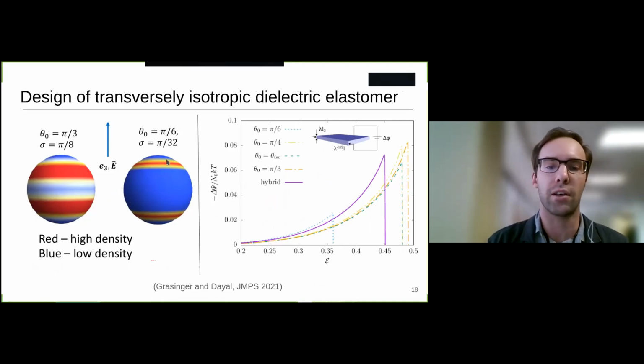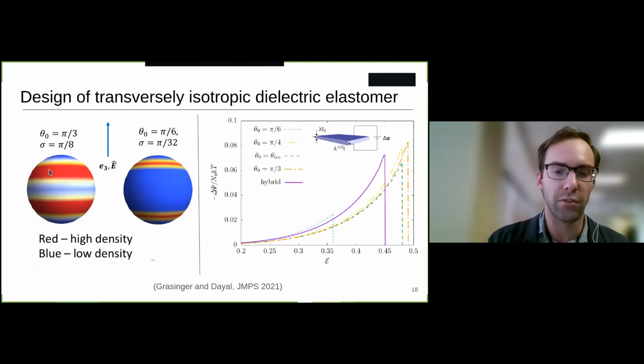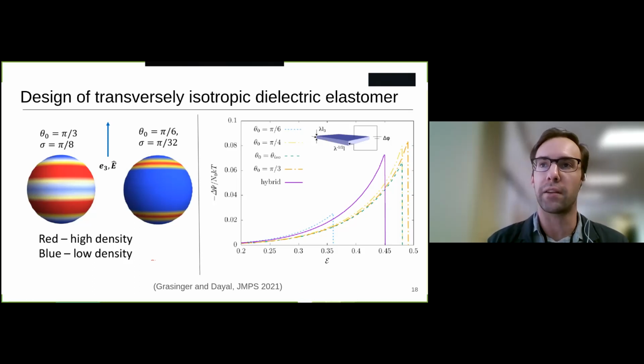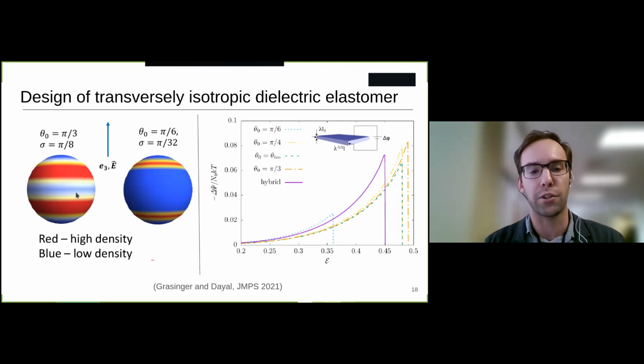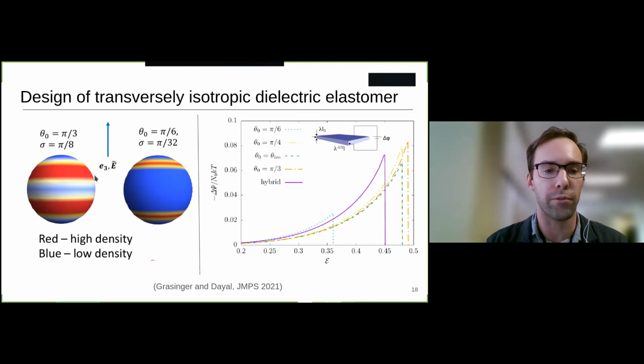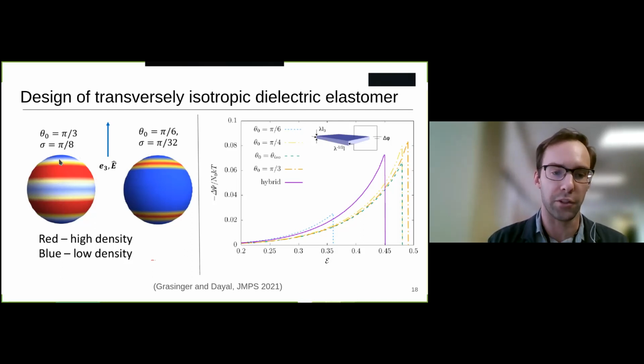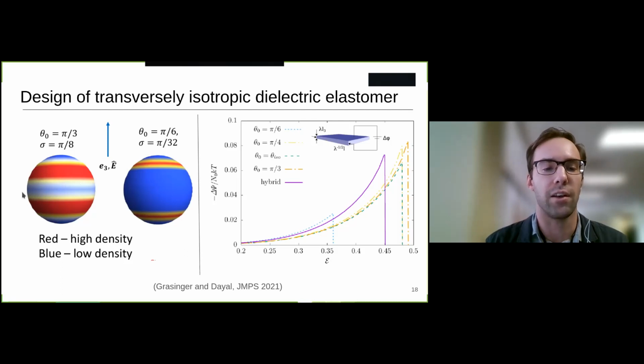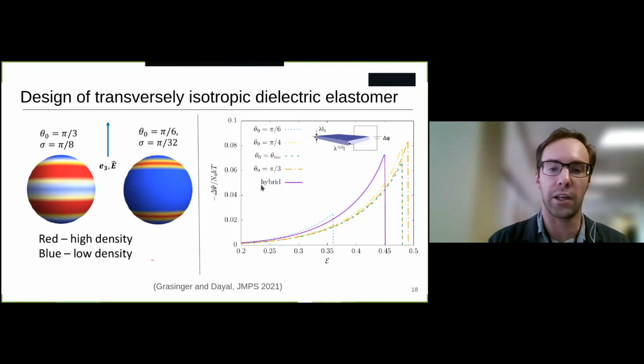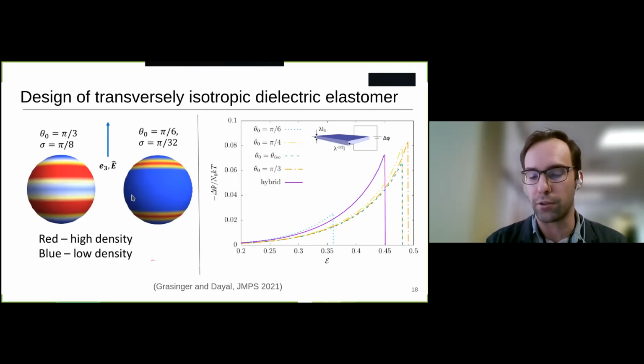And you can also think about what that means in terms of the material design. So here, what we did is we thought about the importance of the chain's orientation with respect to the electric field. Using that as inspiration, we thought, what if instead of having chains randomly oriented in every which direction in our network, we had some preferred directions where there were more chains oriented, and some less preferred directions where there are fewer chains oriented? That's what I'm trying to show with these spheres. The red regions maybe have a higher density of chains, the blue regions a lower density. And the punchline here is that you can really enhance the amount of actuation per applied voltage that you can get out of these materials by tuning the microstructure in this way.